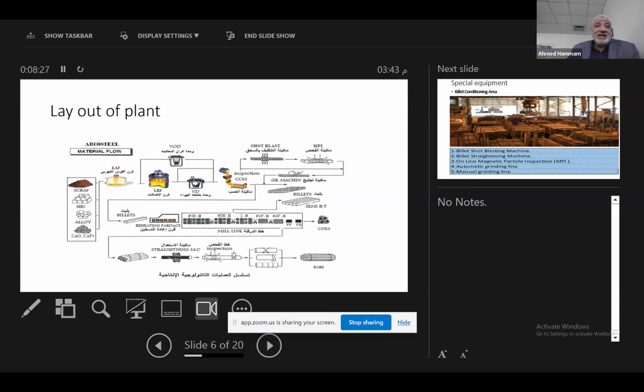Also, we are doing the grinding for the billet. This grinding is done by manual grinding or automatic grinding. Then the billet is transferred to the reheating furnace, followed by the rolling stands, normal rolling stands. For our case, we are producing bar in a mill with 22 stands, and in addition, we are producing wire rod in 32 stands.